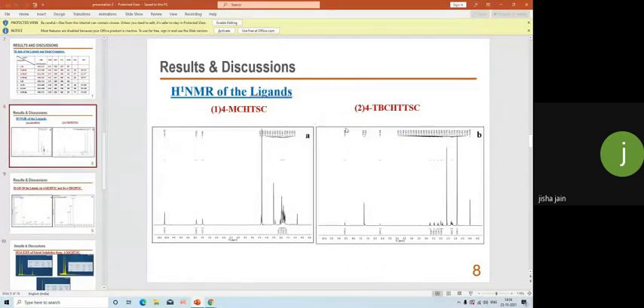Then proton NMR of the ligands. First, 4-methyl cyclohexanone thiosemicarbazone. In that, the NH proton gives a peak at 10.153, and the NH2 protons give two singlet peaks, one at 7.919 ppm and 7.492 ppm. This indicates that the two hydrogens of the amino group are not in a chemically equivalent environment. The CH3 group present at the fourth position of the cyclohexanone ring appears at 0.65 ppm, and the remaining peaks correspond to the different hydrogen atoms present in the cyclohexanone ring system.